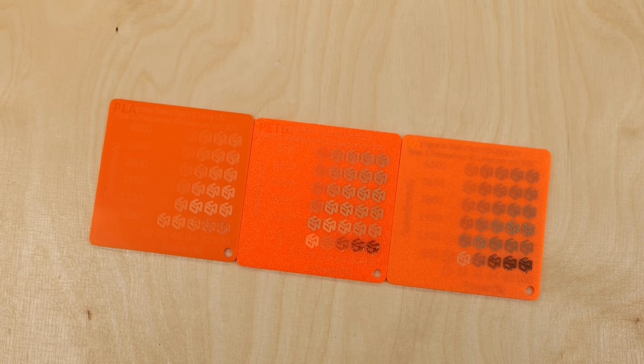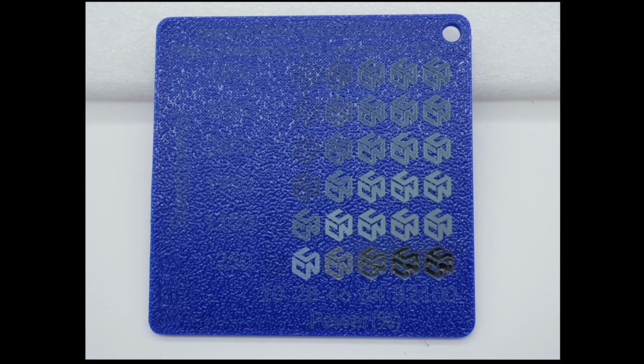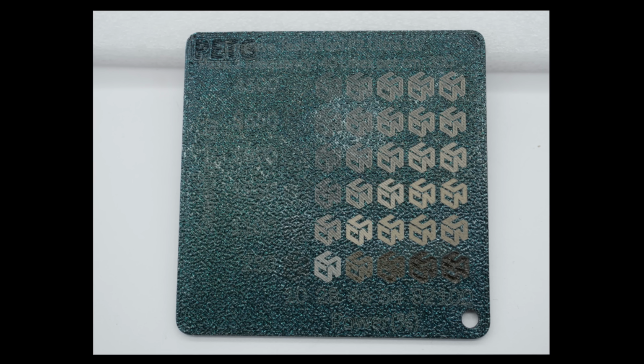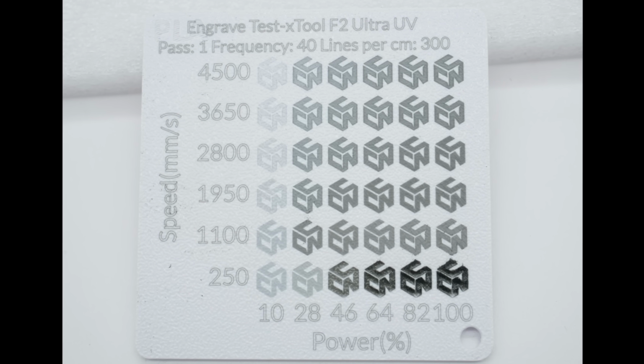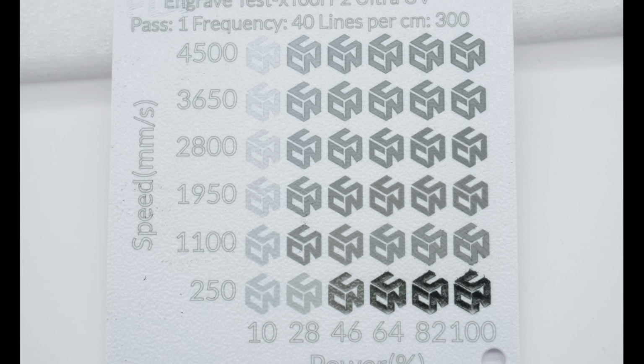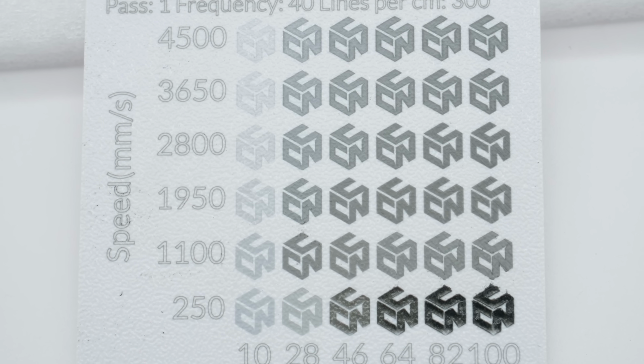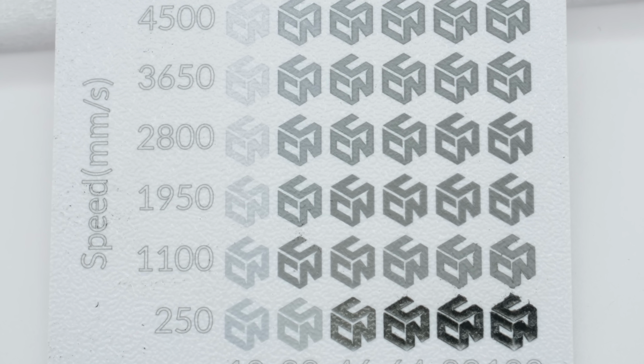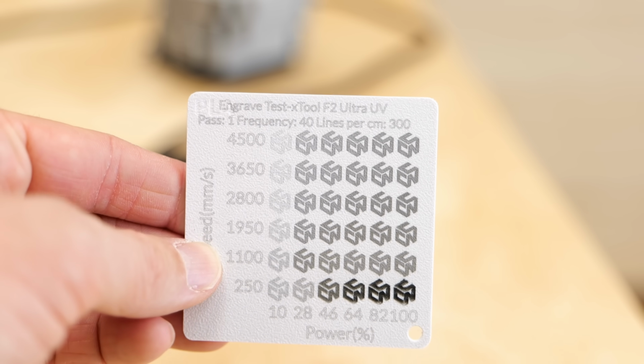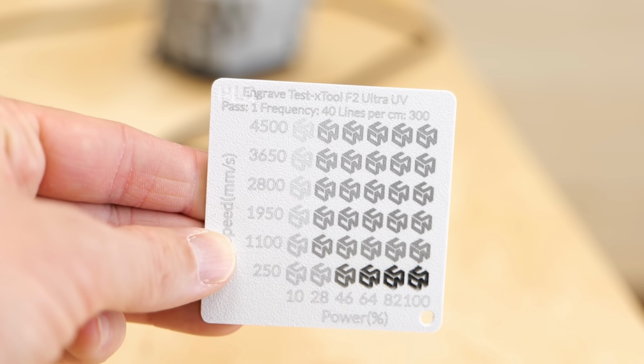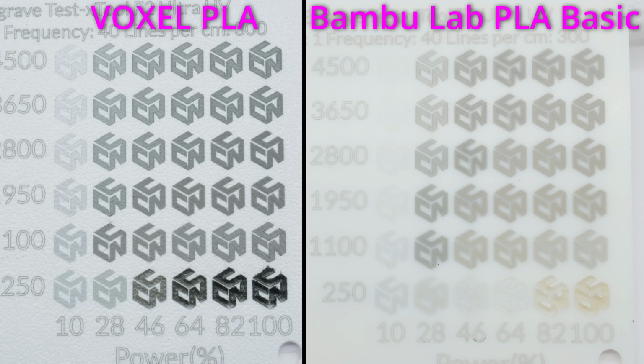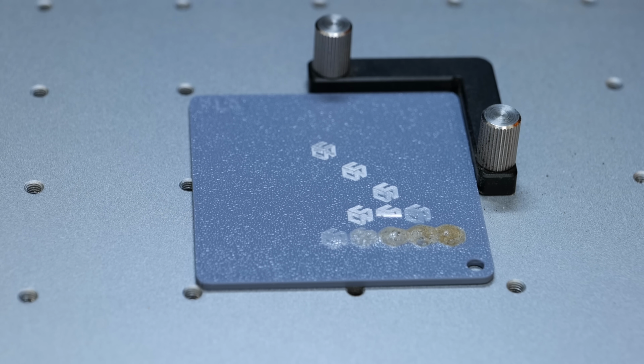Though there were still some material differences. Some plastics foamed more easily, others changed color without much surface texture, and sometimes the filament manufacturer even made all of the difference. The clearest example of this was the white PLA. The white Voxel PLA gave me probably the most impressive results of the whole test. The contrast was unlike any of the other samples and it marked beautifully dark, but the Bambu Lab white PLA behaved much worse. Similar color, also PLA, but completely different results. This is exactly why you cannot just say white PLA works or white PLA doesn't work. The pigment and the additives can make a ton of difference.